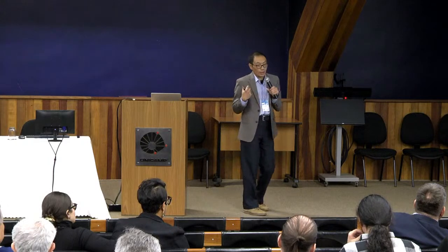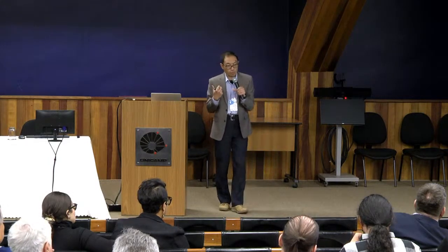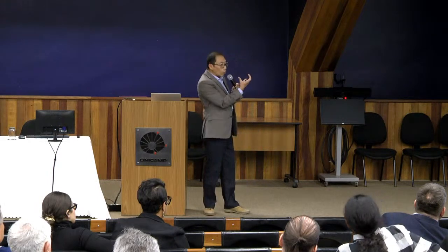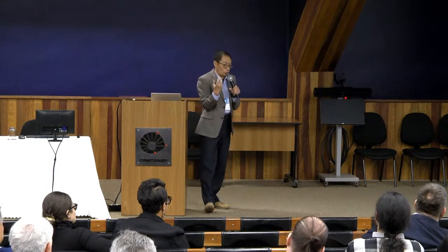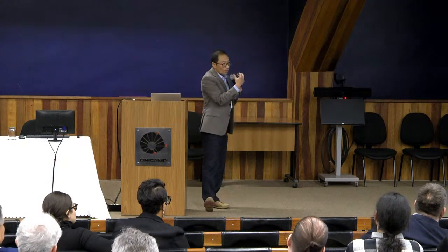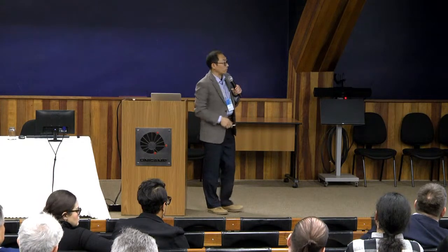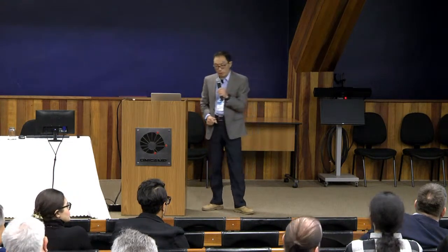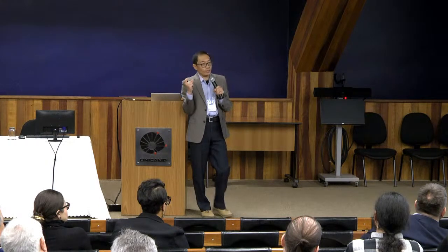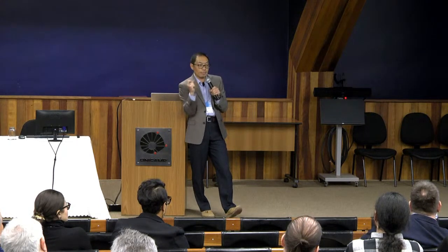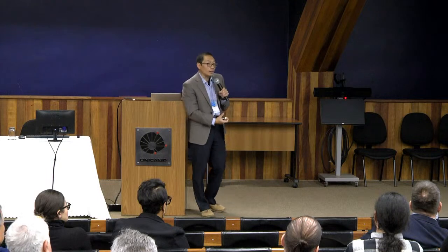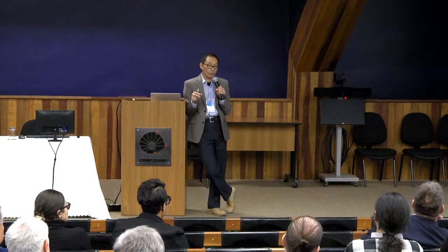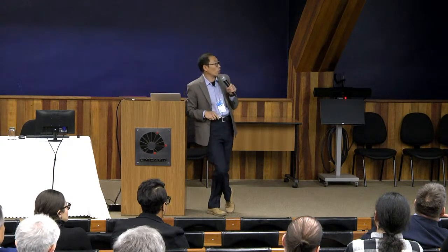That's what we see in the RIXS. However, it seems to us more and more like a very local structural distortion, or a defect, if you dope it. So it's a structure-related phenomenon, a very local structure-related phenomenon. The other thing, to me a more important one, is that O-O bonding is a chemical definition of oxygen oxidization. As I mentioned, physically, we define the pulling out of the ligand hole as oxygen heavily involved in the redox, or oxygen getting oxidized, you can call it that way.